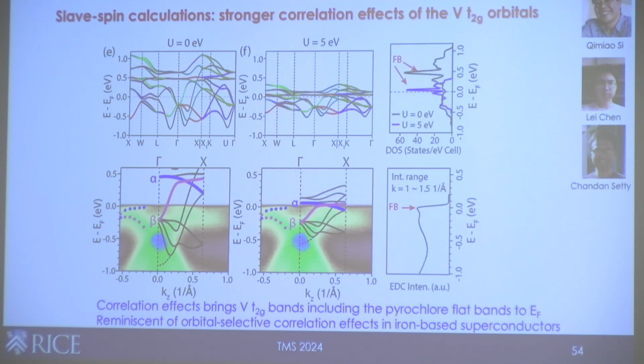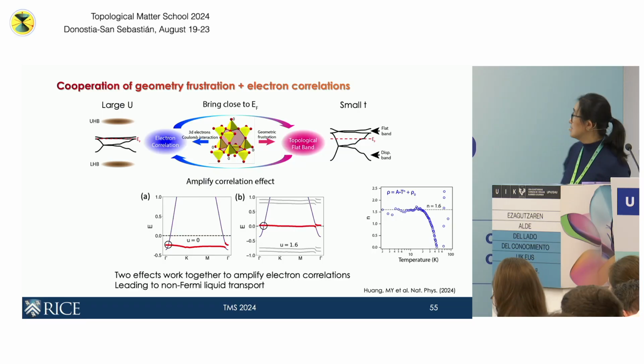So what can we do? We talked to Timel, who's next door. Basically, they did a tight binding fit of the vanadium T2G orbitals near the Fermi level. And then when they crank this through the slave spin calculations, incorporating the equivalent interaction U and Hund's J, they can see that they can renormalize the flat band closer to the Fermi level together with all the other dispersive states near the Fermi level. So you can see the mapping is actually much better to our data after the incorporation of these correlation effects on the vanadium T2G. This suggests that in this material, we see two effects.